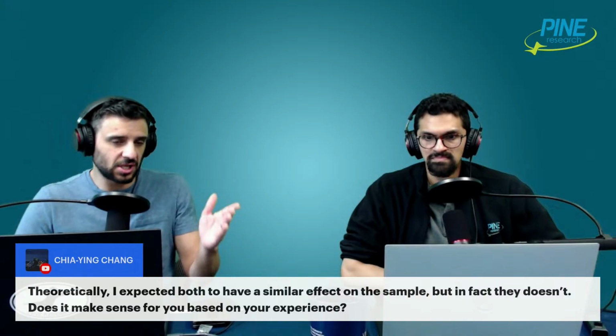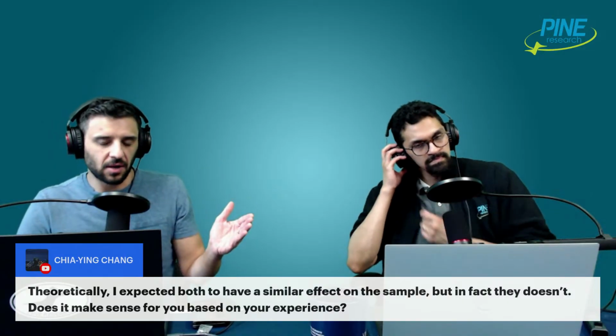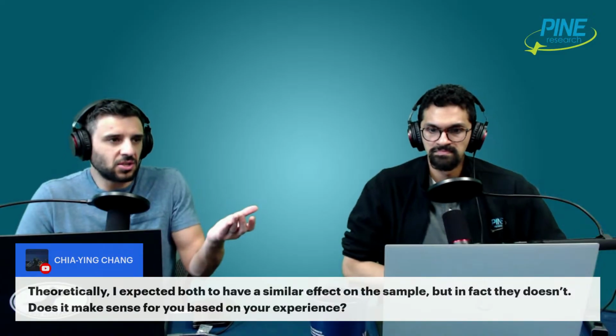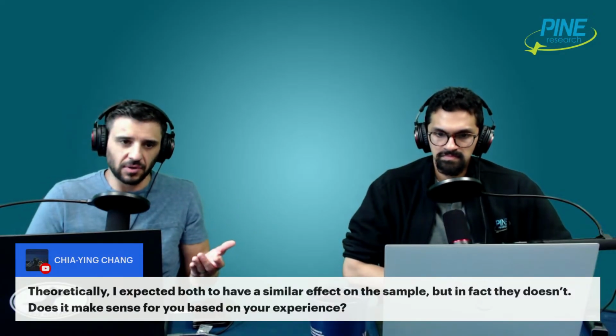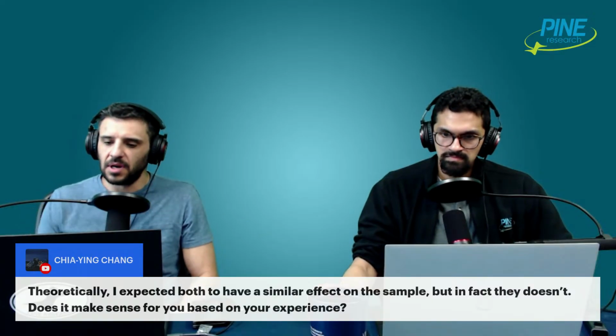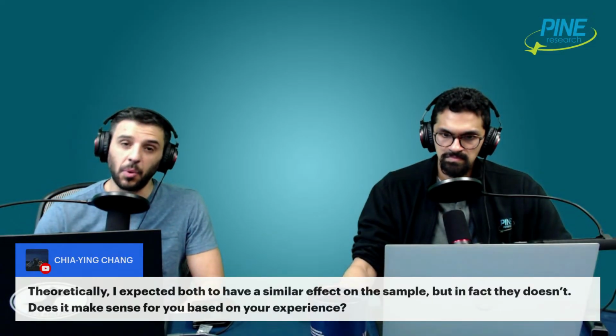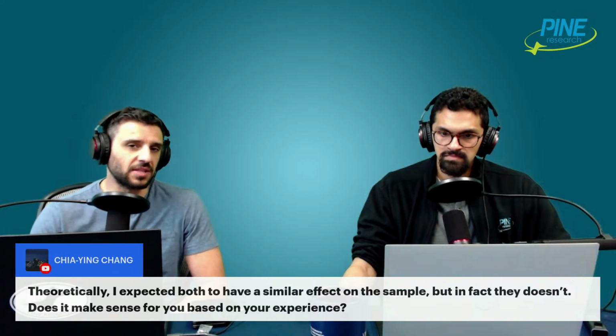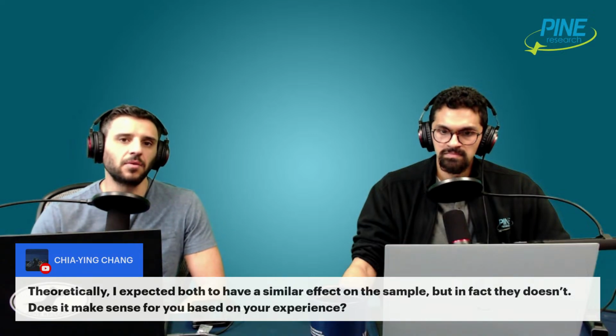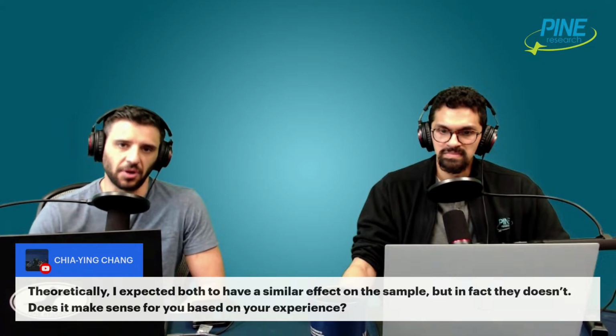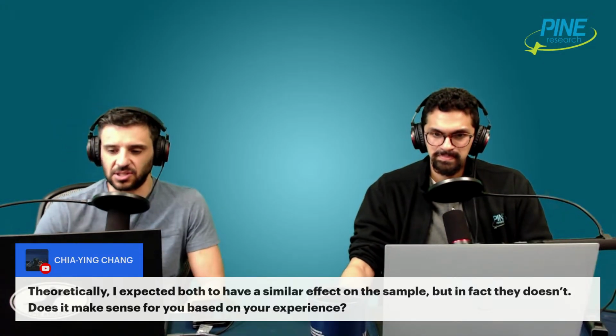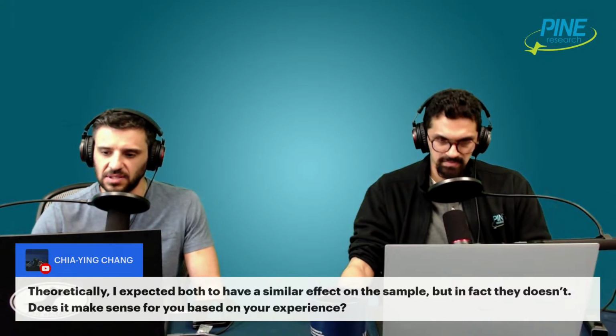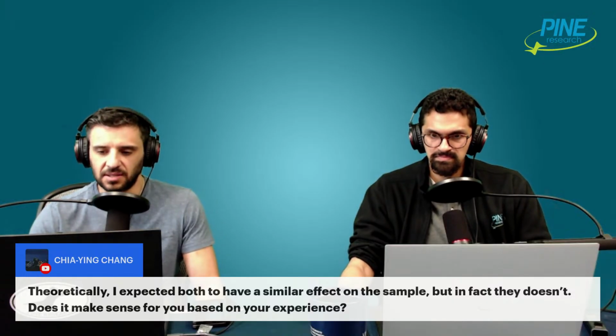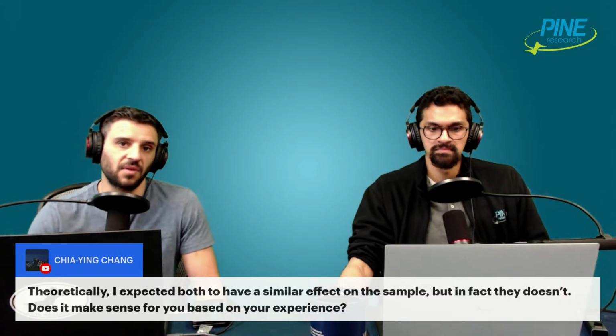Whereas when you're controlling the voltage in a system where we really don't want it to go haywire, you're not in danger of ripping apart the electrolyte or the electrode because of the voltage going up to 5 volts or something weird. And that is not good from the perspective of, well, I really want to get 0.18 amps all the time because I'm trying to generate a lot of product. And the reality is you can't do that without the voltage going crazy. That's what you're learning. So that's just sort of a thermodynamic limitation, or whatever you want to say, something of that nature. But yes, generally, to answer your question, it does make sense. So if you're seeing that, I don't believe you're doing anything wrong fundamentally.